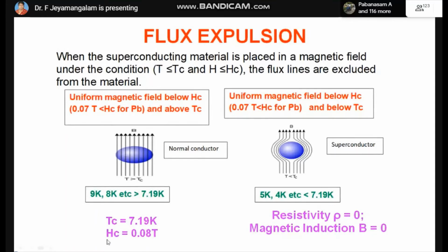For your understanding, I have given the critical temperature for lead as well as the critical field for lead. You have a lead specimen in the shape of a ball. In that, with the uniform magnetic field, the flux lines are penetrating through this material. So the material is in the normal conducting mode above the critical temperature, say 9K or 8K. In the second part of the experiment, the field remains the same, but it is cooled below the critical temperature, 5K or 4K. So the temperature is reduced below its Tc.